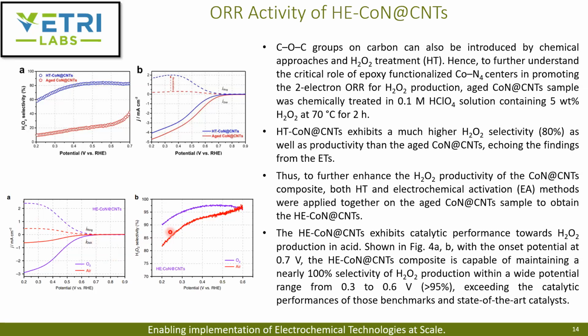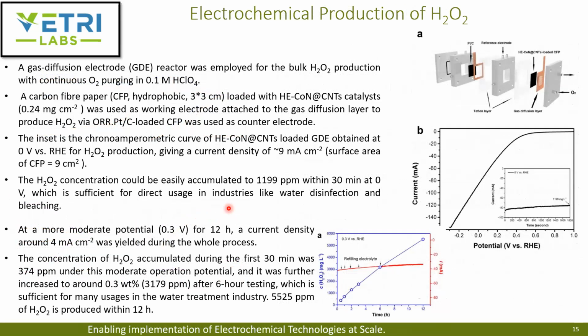When they measured the selectivity, they could see it maintained nearly 100% selectivity over a wide potential range, and at about 0.3 to 0.6 volts it maintains about 95%, exceeding the catalytic performance of the state-of-the-art or other benchmark catalysts reported in the literature for this M-N-C based material. Further, they did the electrochemical production of peroxide by assembling a gas diffusion electrode reactor with oxygen purging on 0.1 molar perchloric acid.